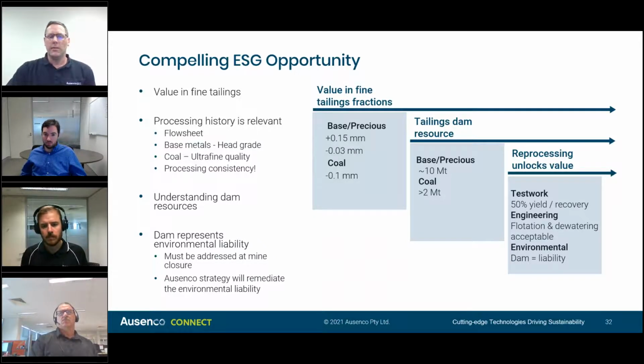We then need to identify the amount of valuable material in the dam resource through test work and engineering. So we've done metallurgical test work for both the coal and base metal industries, and it indicates that the dam resources can achieve yields or recoveries of 50%. We've done additional engineering that confirms that the flotation is suitable and the dewatering is acceptable for a marketable product.